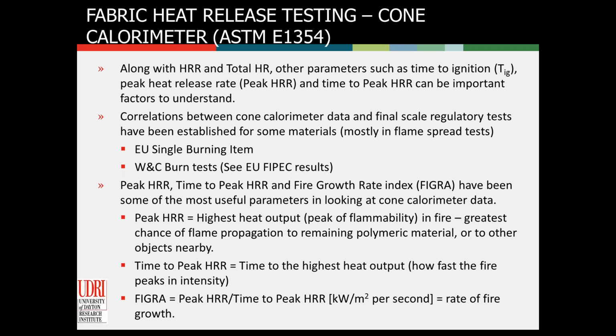The fire takes time to build up, or does it instantaneously ignite, go rapidly to peak heat release rate, and then suddenly burn itself out, indicating you'd have a very quick flash of fire once the material ignited. You can also look at some of these composite measurements like fire growth rate, or FIGRA, where you take the peak heat release rate and divide it by the time to peak.